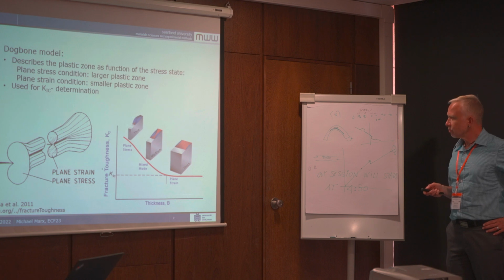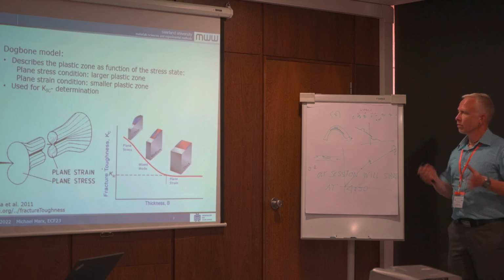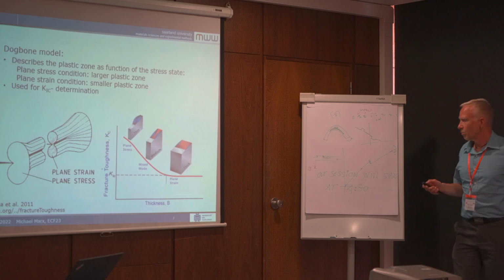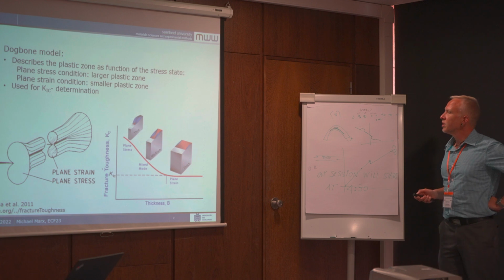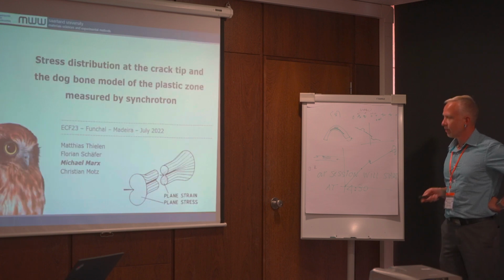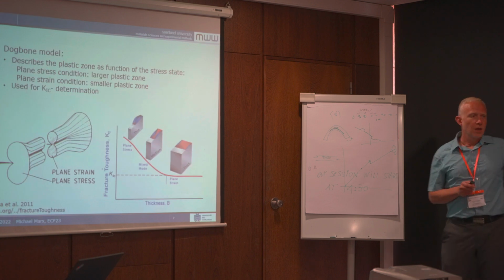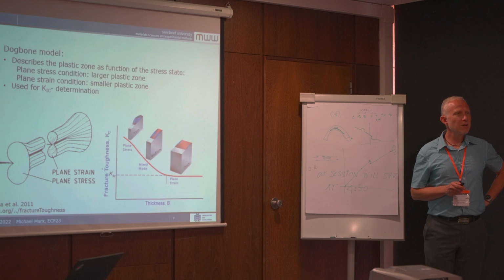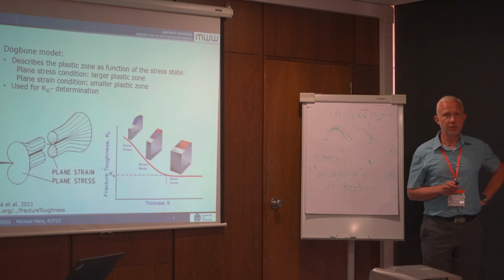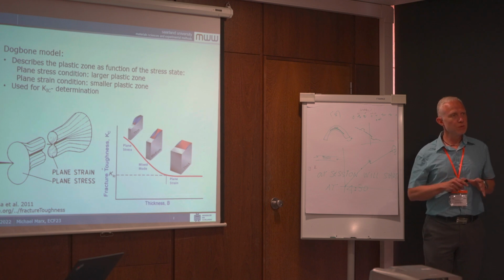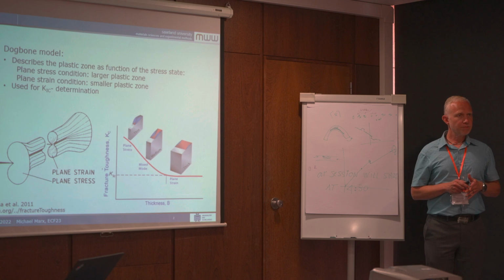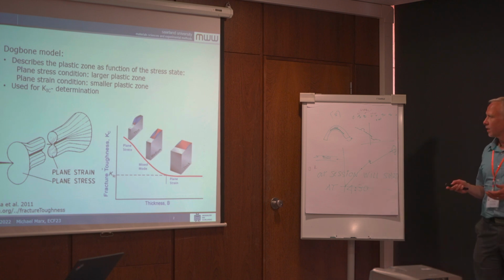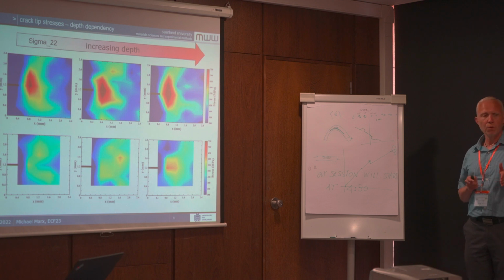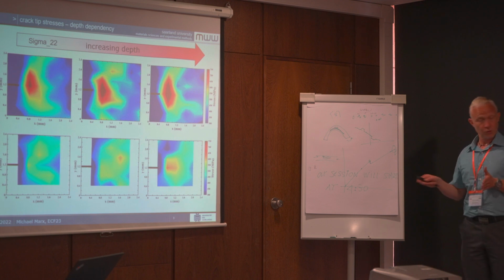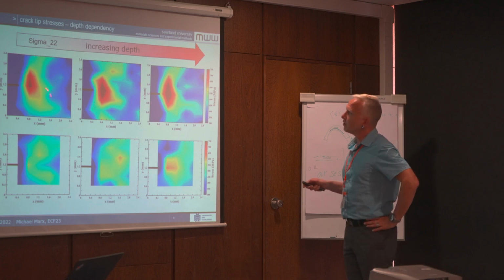Actually, we were not interested at the beginning in this three-dimensional shape of the plastic zone. My PhD students, I should mention Matthias Thielen and Florian Schäfer, who did these measurements at the synchrotron, were interested in the effect of an overload during fatigue, and for this we measured the stress in front of our crack tip. From the synchrotron data we then got the idea that we have the information about the stresses with depth resolution also, not only at the surface but also in the depth. And this is what we found before the overload.